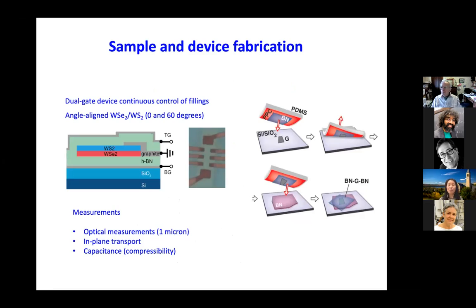The way we make those materials, I will not say too much, just a few words. We use the so-called Scotch tape technique to make those devices. You come up with a very clean substrate, usually silicon, clean and flat, and first exfoliate your bulk crystal. Then there will be some flakes left on your tape. You put down your tape on your substrate, and by statistics, somewhere you will leave one monolayer or bilayer or trilayer, some thickness of flakes behind. But that flake is only in touch with the silicon substrate and nothing else. It's clean. So we can use optical techniques to identify which one is one layer, and also to determine the crystallographic orientation.